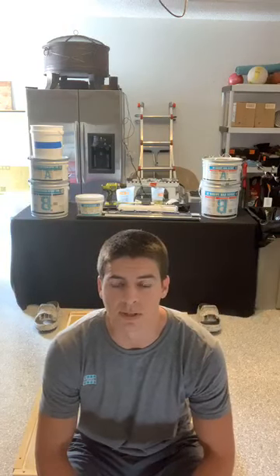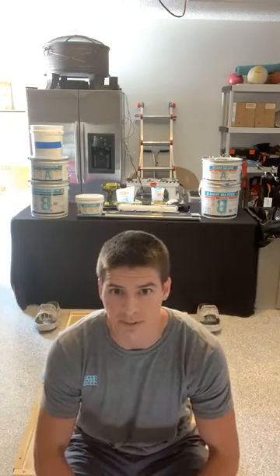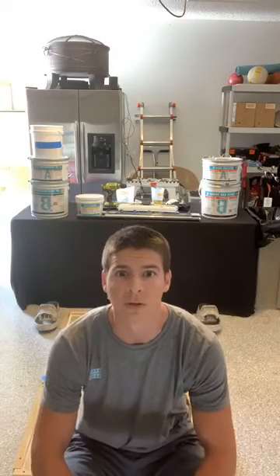Okay. One big misconception that we get all the time is that a broom finish has texture, right? Well, it's still closed. That's actually surface cream of the concrete. You pull a broom on it, and that texture gets mistaken for porosity. All right, that is absolutely not the case. So that's why we open up these floors with mechanical means, so our 100% solids epoxies can penetrate into the pores of this concrete and create a bond strong enough that the concrete will fail before the actual coating does.